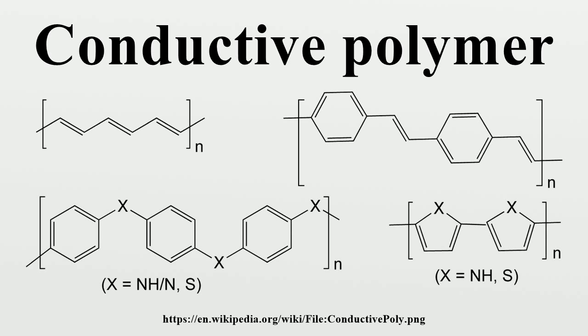dispersibility. With the availability of stable and reproducible dispersions, PEDOT and polyaniline have gained some large-scale applications. While PEDOT is mainly used in anti-static applications and is a transparent conductive layer in the form of PEDOT:PSS dispersions, polyaniline is widely used for printed circuit board manufacturing, in the final finish, for protecting copper from corrosion and preserving its solderability. Electroluminescence. Electroluminescence is light emission stimulated by electric current. In organic compounds, electroluminescence has been known since the early 1950s, when Bernanose and co-workers first produced electroluminescence in crystalline thin films of acridine orange and quinacrine.